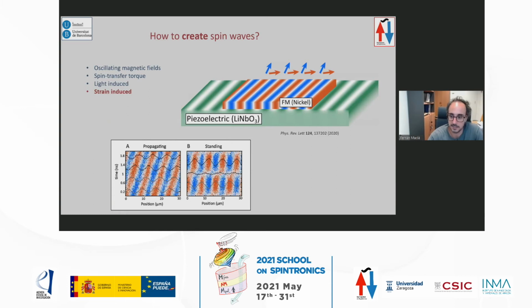Finally, I show you also how to create magnetic waves with strain waves, because this is something I did recently. The nice thing about strain waves is that a 1 gigahertz phonon in a piezoelectric material happens to have a wavelength that is also of the order of microns. So we can match the wavelengths of the piezoelectric and the magnetic material. In principle, because of the magnetoelastic effect and magnetostriction, if you compress and decompress a magnetic material, you can create magnetic excitations.